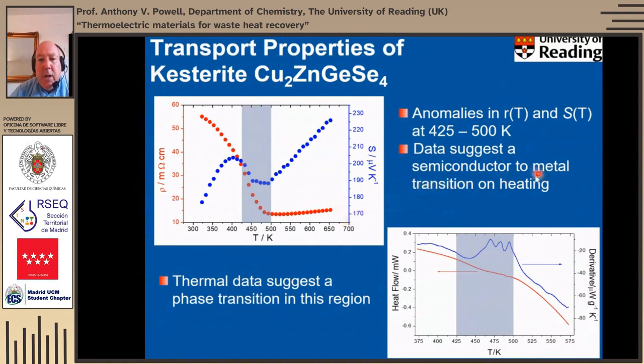Now, as I say, this has been described as a semiconductor to metal transition. I think it's unlikely to be a true metal, because this is quite a high Seebeck coefficient of about 230 microvolts per Kelvin. And it's also quite a high resistivity of about maybe 15 milliohm centimeters to be a conventional metal. So our belief is that it's actually a transition from an activated semiconductor to a degenerate semiconductor.